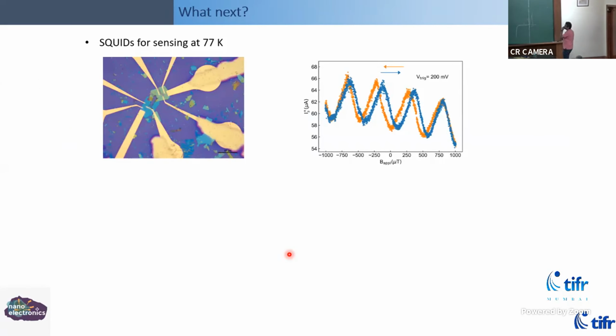So what next? We have already made, Amit has actually made SQUIDs, which are essentially two Josephson junctions in parallel with a loop in between. And when you thread flux through this, for every quantum of flux that goes through it, you see an oscillation, and that's what you see here. It's one of the ways to measure magnetic field very sensitively. So these are at 77 Kelvin.